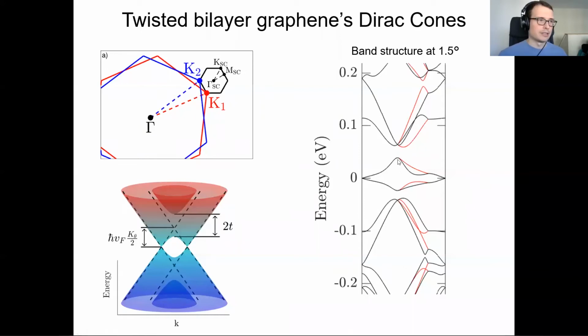The difference is because you have two sides, unlike the harmonic oscillator, where you're able to make a low energy band and then keep adding them up as you go higher in energy, you're getting these hybridizations on both sides of the band structure. And so this is why graphene has what's called a magic angle, or a precise tuning. You need the hybridization on the top and the bottom to exactly cancel each other out to create a flat band.